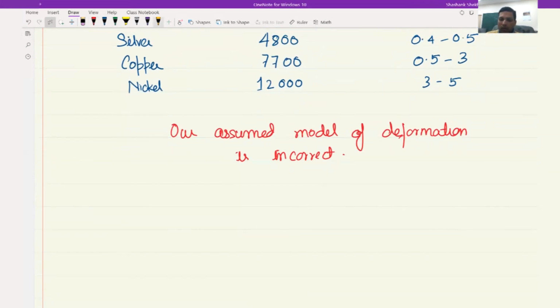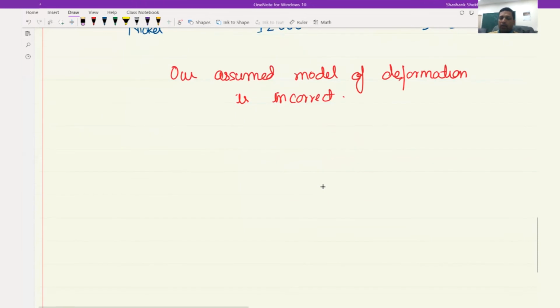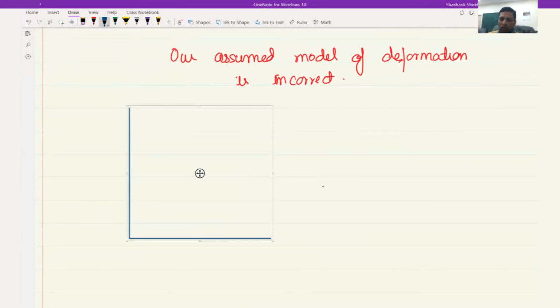Moreover, if you look at the value of flow stress as a function of what is called the dislocation density, of course we have not yet defined it, but if you look at it now, just going a little bit ahead of ourselves, this is how it looks. On the x-axis we have increasing dislocation density, and on the y-axis we have flow stress. So when the dislocation density is very low, then the flow stresses are very high. In fact, it can reach the theoretical values that we just talked about. But in general, an annealed polycrystal would be somewhere over here, which would have 10 to the power 14 per meter cube of density of dislocations.